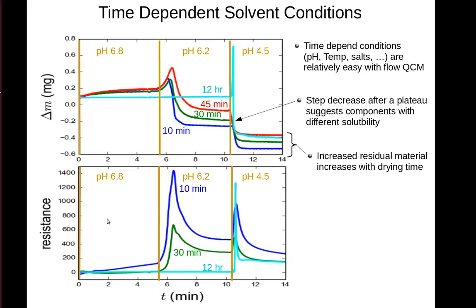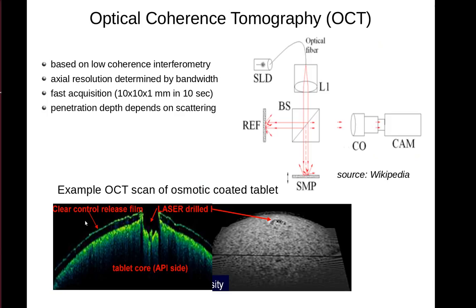QCM therefore provides a relatively quick way to screen the dissolution rate of polymers under different conditions and using different properties of the polymer or different components to put in with the polymer, such as plasticizers or surfactants. However, it provides no information on the actual visual of how the polymer dissolves. We can use another technique to get some visual information, specifically optical coherence tomography, OCT. OCT is an interferometric technique based on low coherence. We're essentially using a broader bandwidth of radiation.